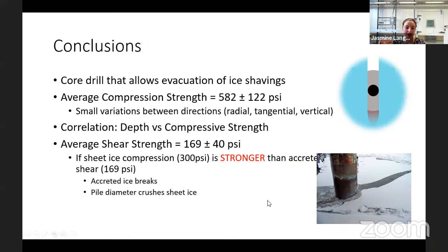And then this brings me back to what I talked about at the beginning. If the sheet ice compression, which is 300 psi per the design criteria for the project, is stronger than the accreted ice shear, which I just determined based on our data is 169 psi, then the image on the right is what we can assume. So basically the accreted ice is breaking off and the pile diameter is crushing the sheet ice, which is also shown in the picture at the bottom right. So that's what we determined from our data.